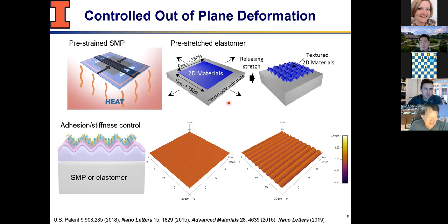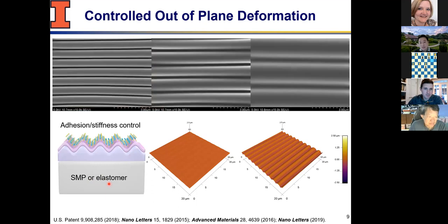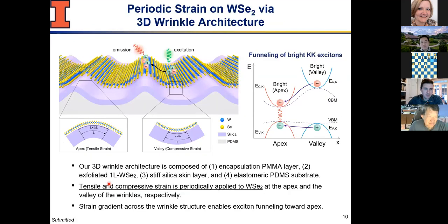You can even add additional interfacial layers to control adhesion and stiffness that allow you to create more conformal and more uniform wrinkles. That's what I'm showing you here by adding a couple more polymer layers on top of either the shape memory polymer or elastomer. You can create much more uniform, almost grating-like structures of these 2D wrinkles. So it depends on what length scale matters and what amount of local strain you're looking for, because length scale, radius and curvature parameters would change. But nonetheless, you can do this with a decent control of the curvature length scale.